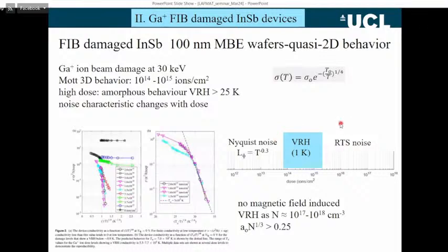What we also find is at very, very high doses, 10 to the 16, 10 to the 17, we tend to introduce so-called RTS noise, which is random telegraph signal noise. So we see this two-level switching behavior coming in, which masks any form of electronic noise. It's very dominant.